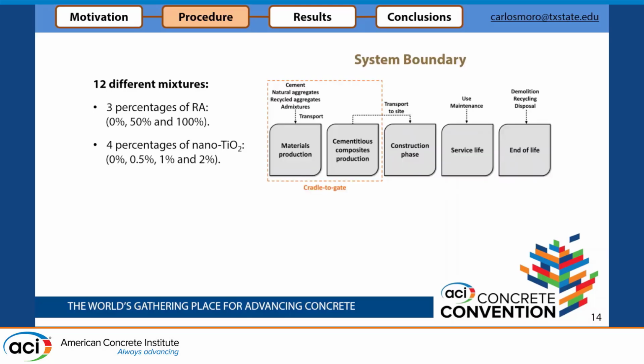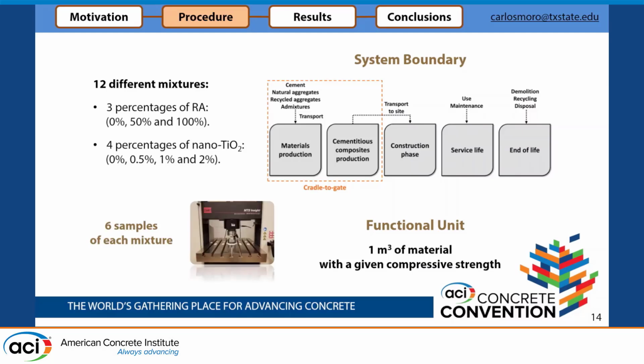We did the system boundary as a cradle-to-gate, but I'm going to mention later what happens later on. Okay, so we also have some hypotheses of what happened next. And as a functional unit, we're going to use 1 cubic meter of material with a given compressive strength. That means that we did compressive strength, and then we modify the cement content in order to equalize and achieve the same performance for all the mixes.